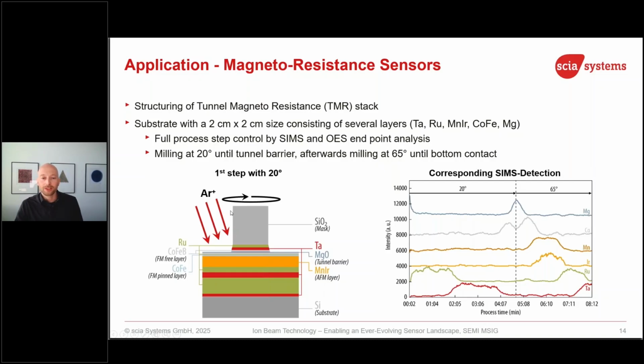And if we want to etch through those layers with RIE, for each layer the wafer would need to go into a different chamber. If we use just argon ions, I showed that ion beam etching works basically on any material. We can etch nicely through the layers. And we do this actually in 2 steps. So first step, we have an angle of incidence close to perpendicular, in that case 20 degrees.